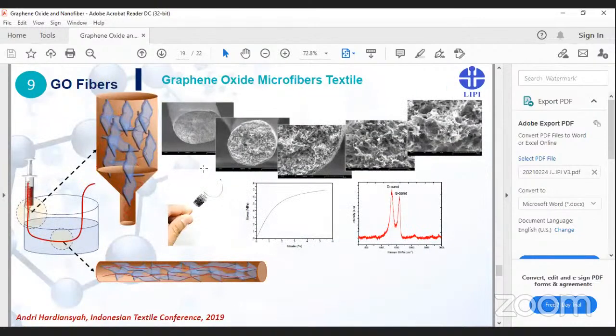And some morphology or structures that we can develop using the graphene oxide is the fiber structures or fiber morphology. Herein, I use the wet spinning in order to prepare the microfiber textile by using the graphene oxide, and it's quite interesting because there is some porous morphology of the fibers, and then of course there are some mechanical properties we can get, and then probably it can be used for a sensing application in the future.